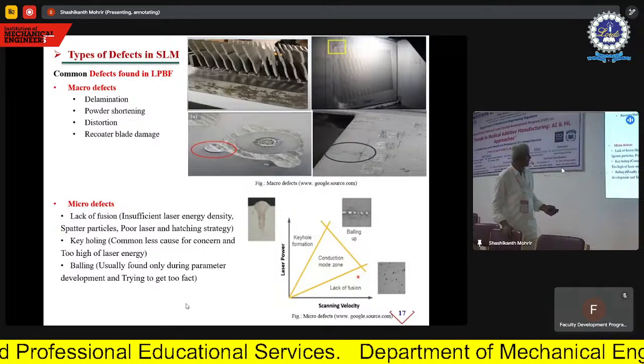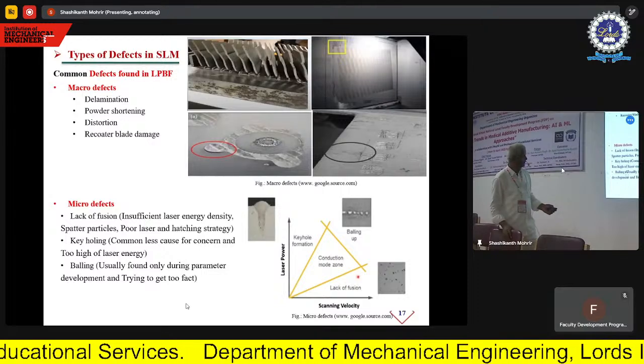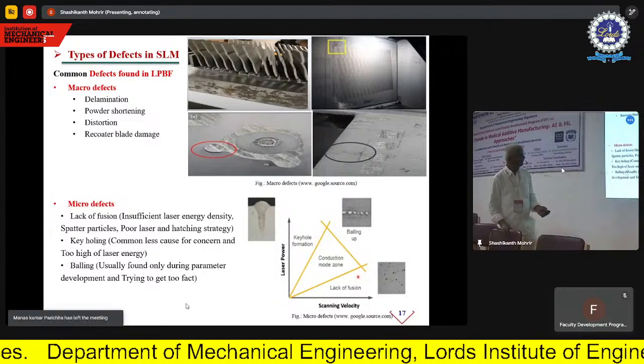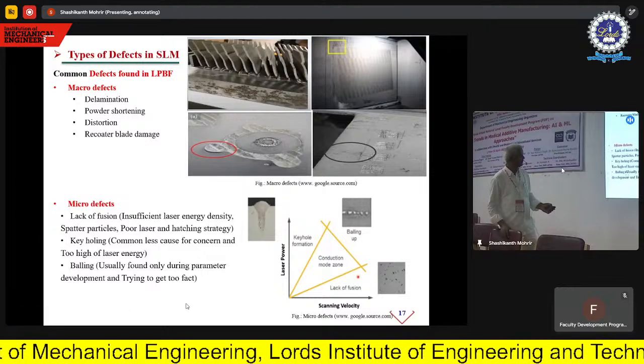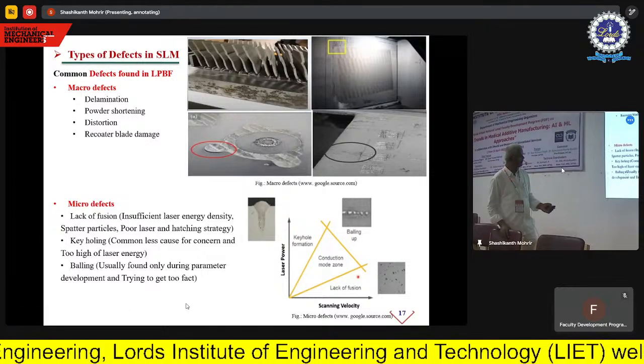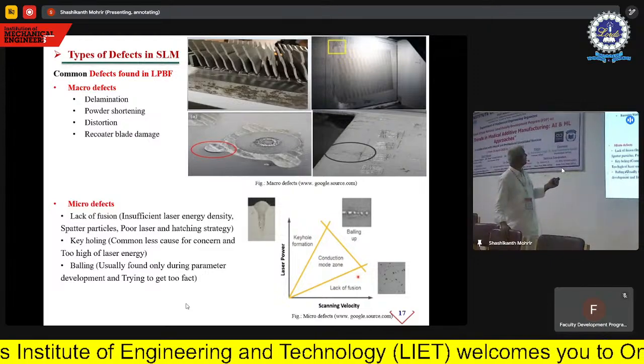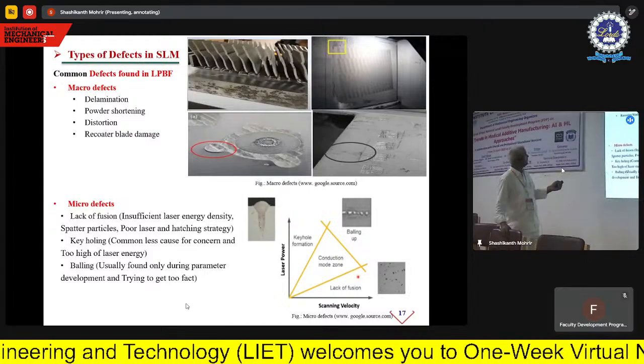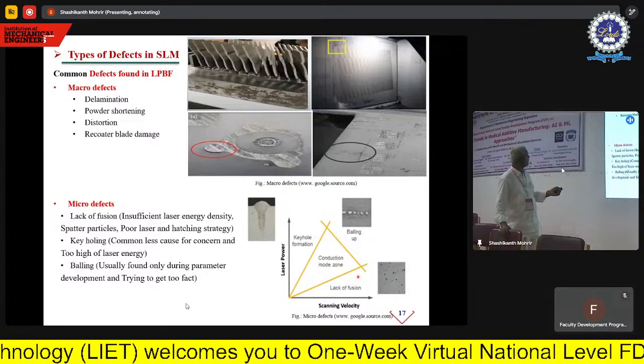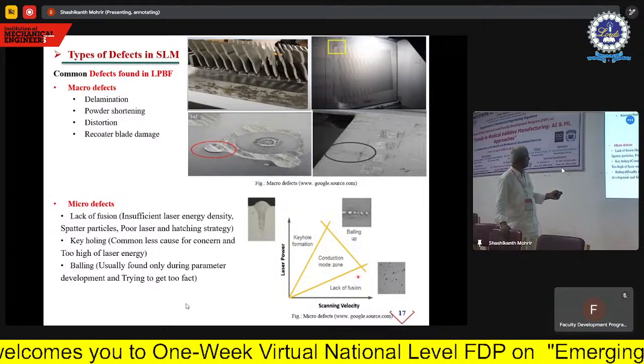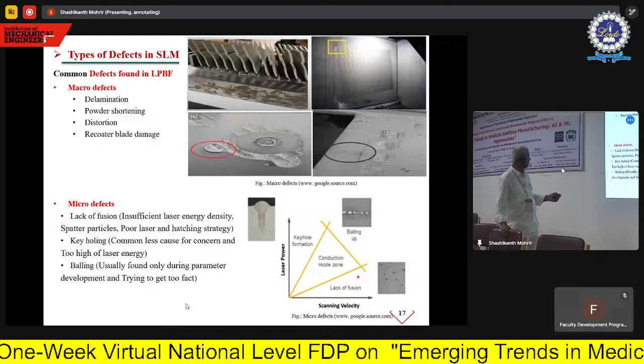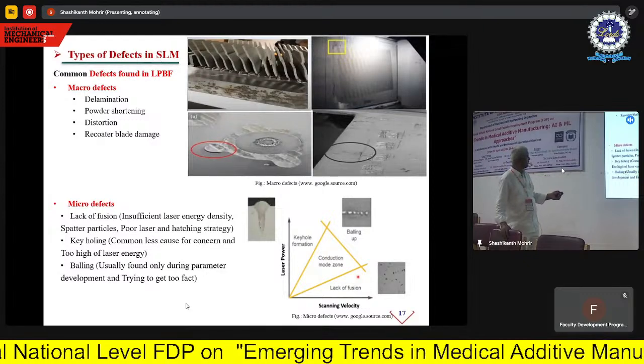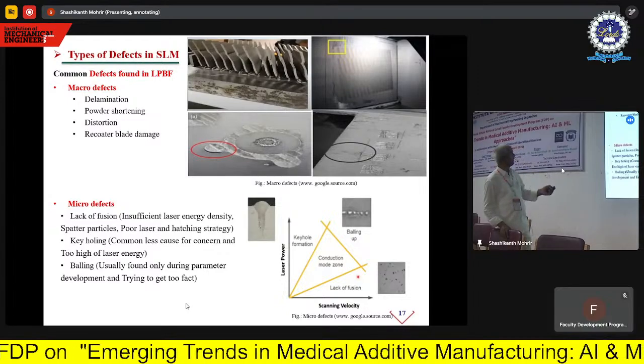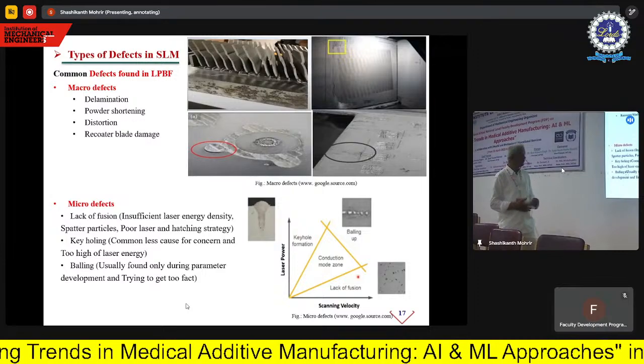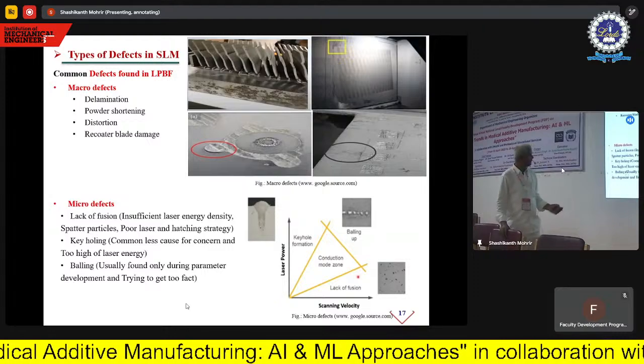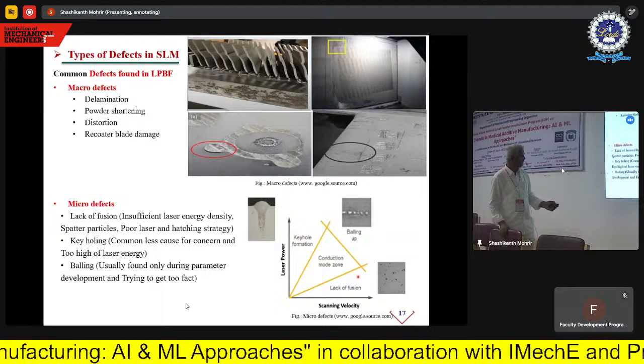Okay. So this is the direction information for us to go and do some work in this area. So common defects: delamination, powder shortening, distortion, recoater blade damage, and micro defects, macro defects, lack of fusion, keyholing, keyholes you have, and balling. So these are micro defects and these are macro defects that will be obtained by 3D printing. So you have to avoid these things first. So to avoid this, you have to have some guidance from this zone. Okay.